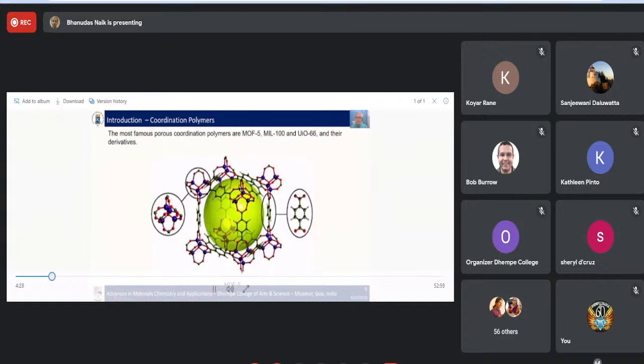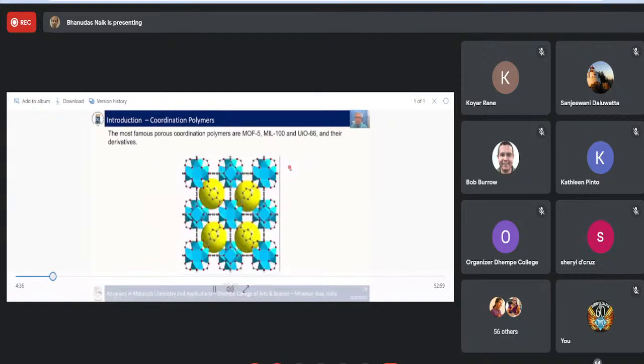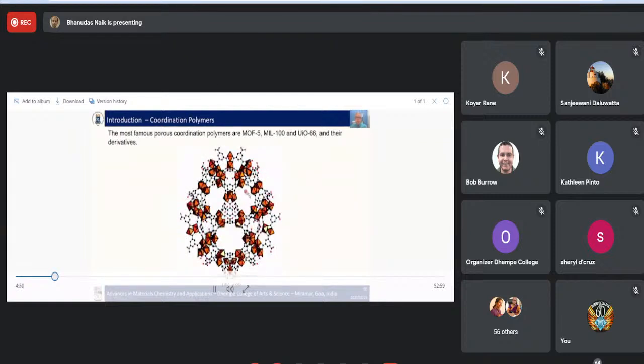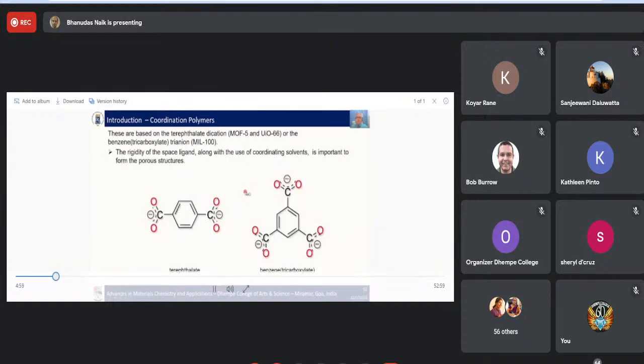This is an example of MOF-5, and this big green ball here shows the void space in the middle, which is usually filled with solvent unless you dry it out. This is UiO-66, which has this smaller space. It's a much more stable compound. And you will now have MIL-100, which is based on a 3-coordinate ligand. Most of these compounds are based on the terephthalate dianion, in MOF-5, and of course all the MOF compounds from Yaghi, and UiO-66 as well. Férey worked on these benzene tricarboxylate trianions. And these ligands are really quite rigid, which gives porosity.